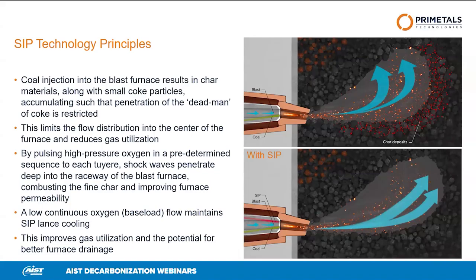Particularly, I guess, with PCI char, which is obviously a challenge for any furnace with PCI, but not a challenge for furnaces without PCI. But combusting, burning out the very small coke particles as well is what the technology can do. And by doing so, you're both extending the raceway and cleaning out the back of the raceway to allow gas further into the blast furnace.